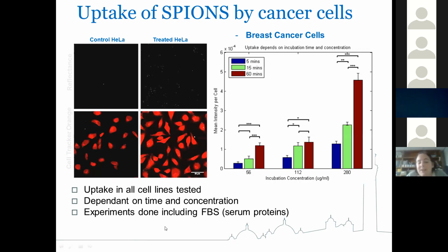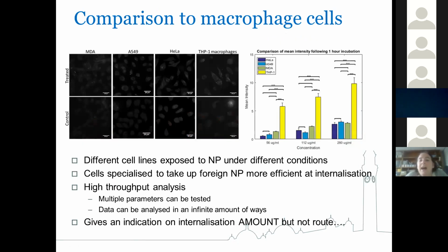And we looked at the uptake in a range of cell lines, and as expected found that it was both incubation time and incubation concentration dependent. So the more particles that were present, the faster they would get internalized. And in all cases, we had serum proteins present, which was important. So we were definitely having the receptor-mediated processes. We also compared to macrophage cells. So these are the cells that are designed for uptake. They're specialized cells for taking up nanoparticles or for taking up foreign debris generally. And as expected, they turned out to be more efficient at the internalization. So what we found using this method was we can very quickly get an indication of the amount of internalization, but not which specific receptor-mediated process the particles were using.